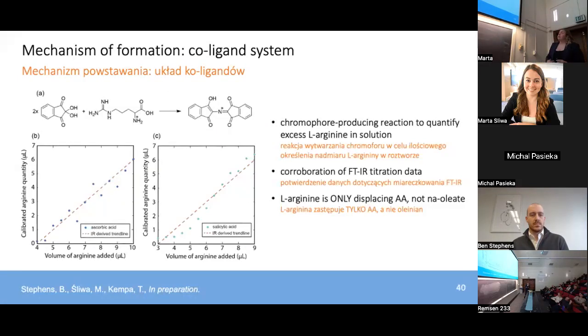So the next thing that we did was to confirm that the L-arginine is only displacing the co-ligand in that system and not interacting with any of the oleate that's also on the surface of those nanoparticles. So we performed experiments to quantify the amount of L-arginine left over in solution after some of it has interacted with those co-ligands. To do this, we introduced ninhydrin, which is a molecule that reacts with L-arginine to form a chromophore with a well-known UV-vis absorbance that can be monitored, and then from that UV-vis we can make a calibration curve. So using that calibration curve, we corroborated the amount of L-arginine that was actually associated with the surface of those nanoparticles via FTIR. So those values were also reflected in these experiments.